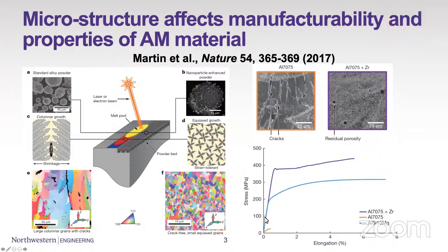But by inoculating it with small zirconium particles, or nanoparticles, they were able to get a finer grain structure. This finer grain structure alleviated a lot of the problems with cracking, and eventually led to a much stronger material, and maybe just as importantly, actually led to a material that could be built with additive manufacturing. So these are two examples of ways in which the process can affect the properties and the buildability of a particular material.